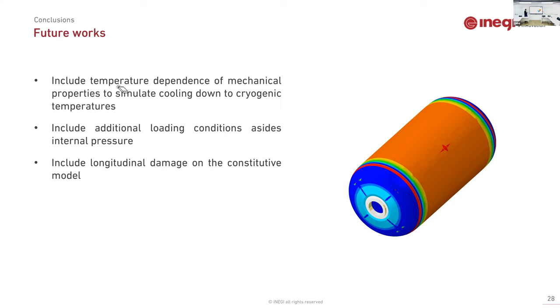For what I am doing, I prefer to do first the thermal part and then the mechanical part using only the temperature field, because I do not have coupled effects, or strong coupling effects. Okay, so the temperature will not change any displacement of the structure. Yeah, that's true. Usually, one-way coupling should be enough in this case. Exactly. Thank you. This is one part. The other part is the failure modes. The failure modes, because at minus 200 degrees, the properties of the material change, transverse strain, and all of the composite properties.